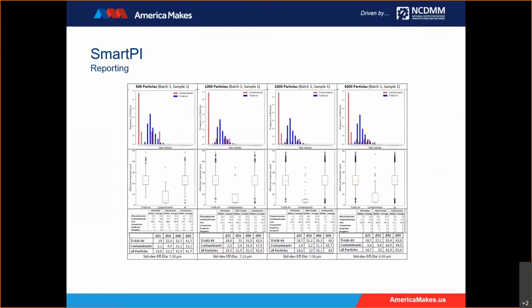We can also create compact reports with all the metrics, like a histogram of the particle size distribution, box plots of effective diameter comparing different classes of powder. So here we're looking at some Ti-64 powder, and so we can also identify any contaminants. We have a table with critical morphological features that we want to track, and the standard D25, D50, D90 that's typically provided by the powder supplier.